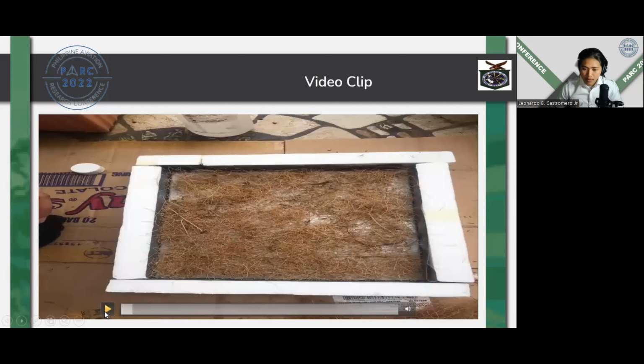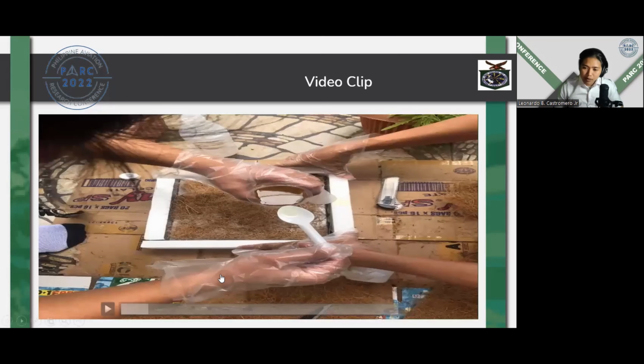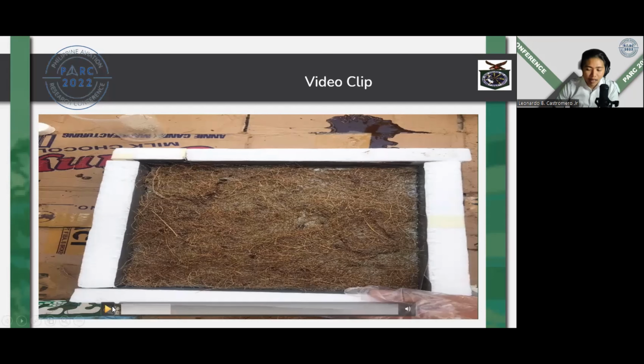This is our first trial. We made a mold using styrofoam and duct tape. Then we put the core fiber on it. After that, you can see in the picture that we are putting our mixture on the core fiber. After several hours, the mixture leaked from our mold, so this was a failed experiment.